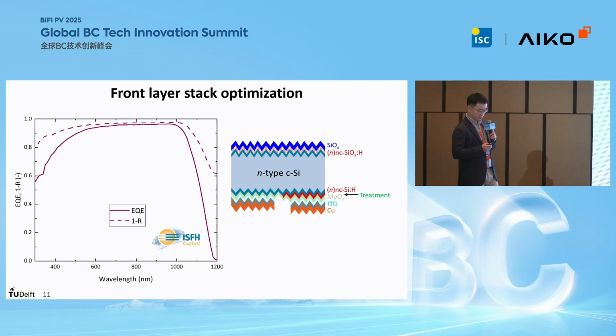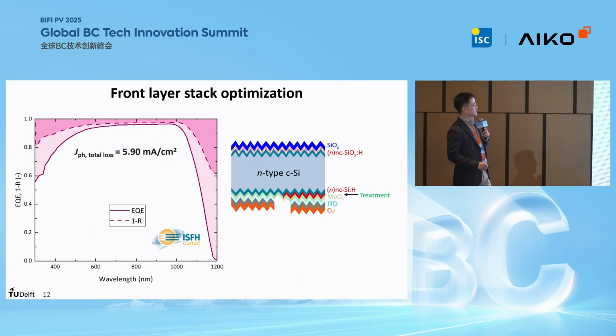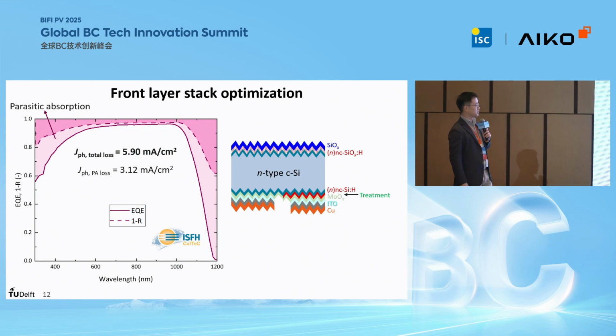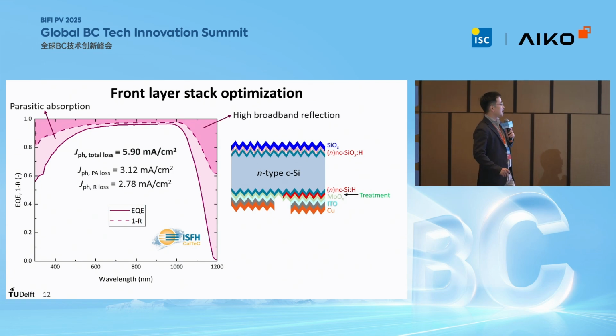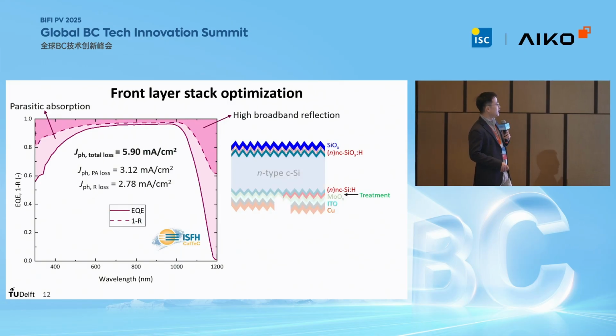So let's take a closer look at the optical analysis of such a device. Here we show on the slide the EQE and also one minus the reflectance curves. As highlighted in pink, the optical losses account for around 5.9 milliamp per square centimeter. The lighter pink accounts for the parasitic absorption loss, which is around 3 milliamp per square centimeter. The cell also features a relatively high broadband reflection loss of around 2.8 milliamp per square centimeter. Therefore, it's very important for us to further optimize this device by focusing on the front-side optical management.